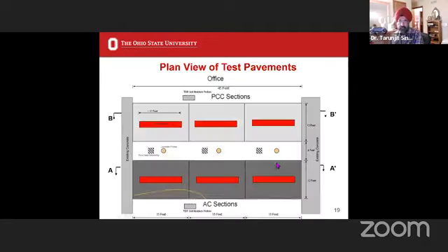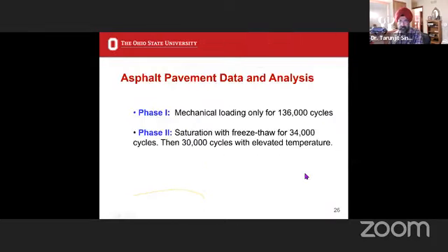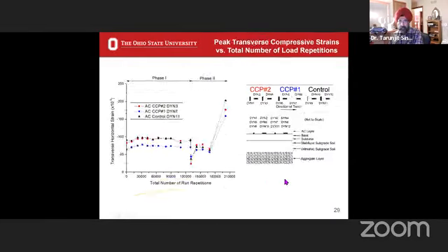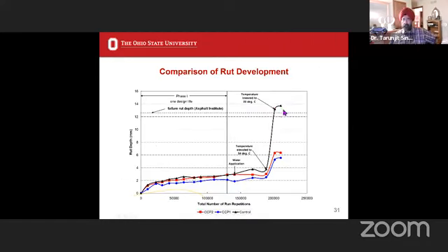And as I think I showed in one of these, there we go. This pavement here that I showed, let me come back here. The rutting depth, the rutting one, here we go. This asphalt pavement has not structurally failed. Structurally, its strength is still there, but in terms of performance, its rut depth has so significantly increased that from a performance perspective, my point is, yes, stiffness governs many, many cases, whereas from a structural failure, the strength does. So I think we both are speaking of two different sides of the same coin, and the two are related to each other.